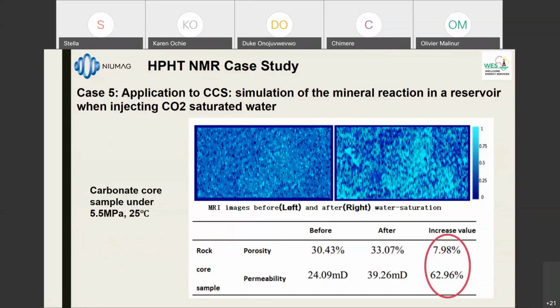You have a carbonate core. Pressure is 5.5 megapascal, and temperature is 25 degrees Celsius. So basically, it corresponds to something at 500 meters depth. And we inject this time CO2 saturated water. And what we observe is that originally the porosity was 30%, and the permeability was 24.09 millidarcy.